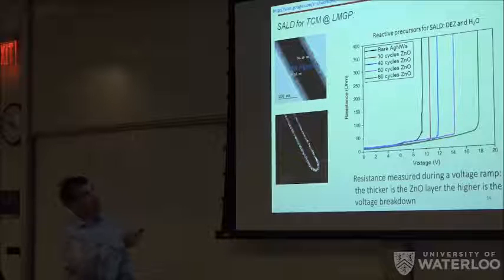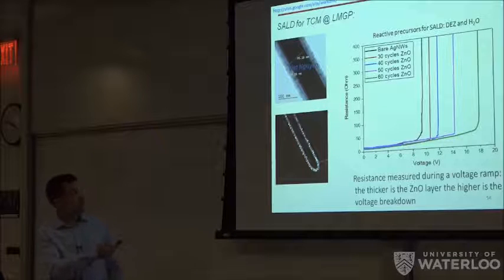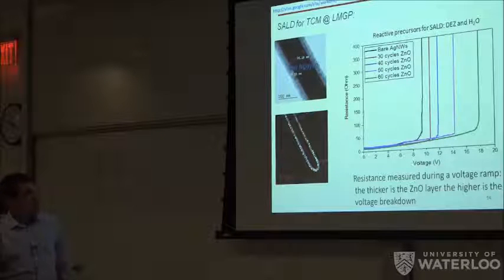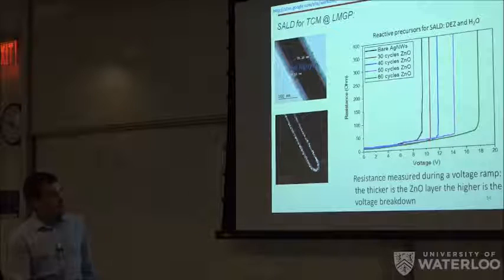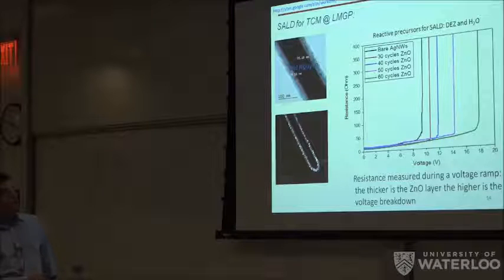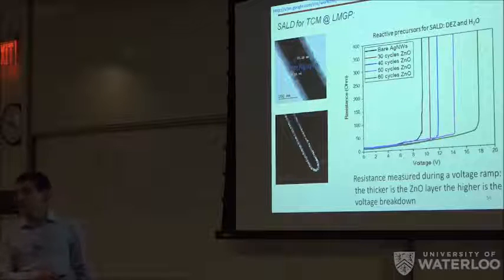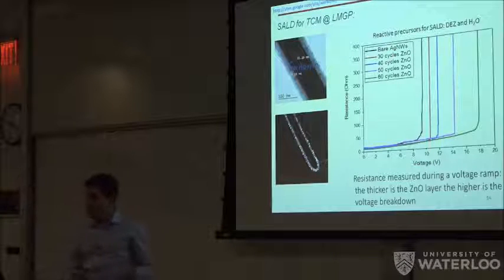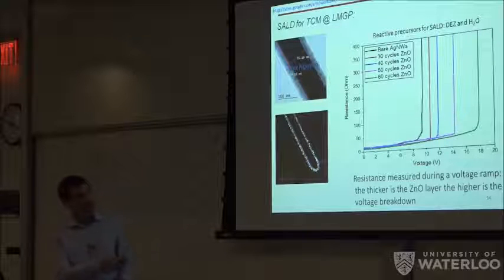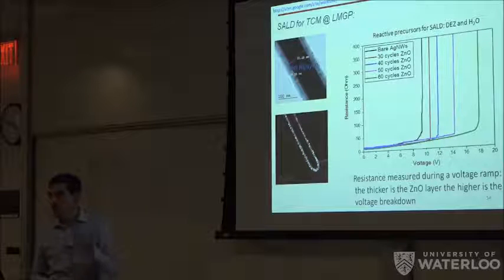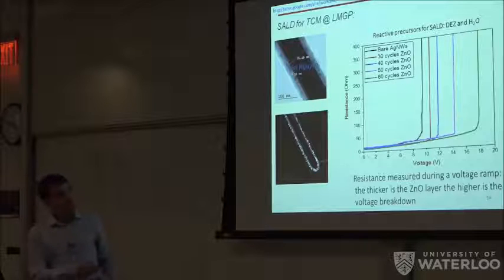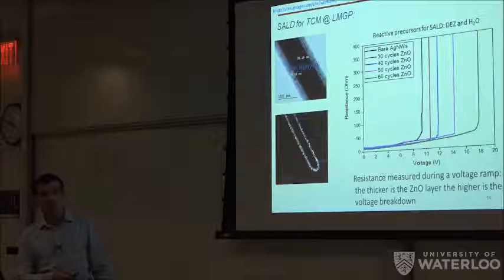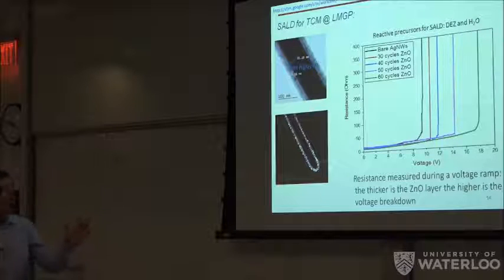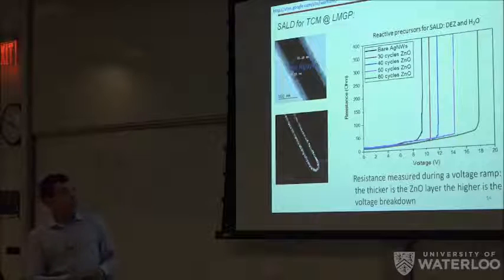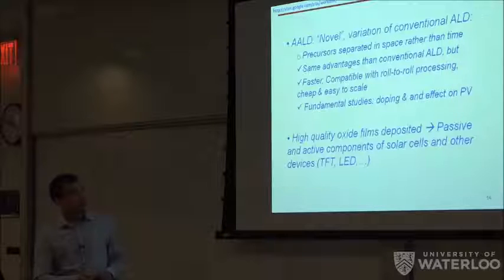This is another example where you have, again, the nanowires coated by the zinc oxide, and again, very conformal. And here is the same. As you increase the voltage, if you don't have protected wires, they will become spheroidized, and your network will be lost, and therefore the resistance becomes infinite. And as you increase the thickness of the coating layer, you manage to increase the amount of the temperature and the voltage that you can apply to your networks. So that's another thing in which we are working.